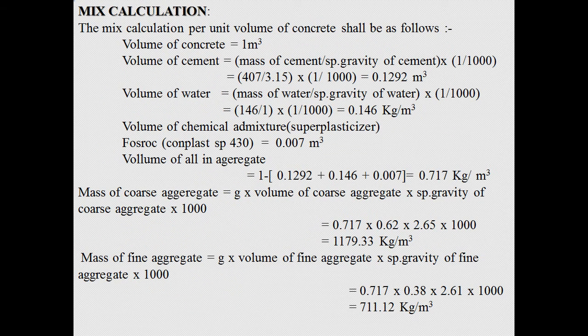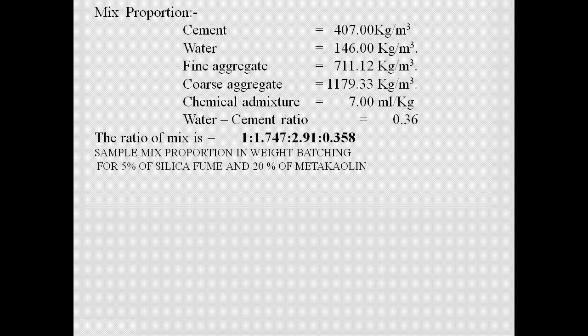And here is the mix calculation for volume of cement, volume of water, mass of coarse aggregate and mass of fine aggregate. Here is our mix design, the mix proportion: cement 407, water 146, fine aggregate 711, coarse aggregate 1179, chemical admixture 7 ml per kg, water cement ratio 0.36.